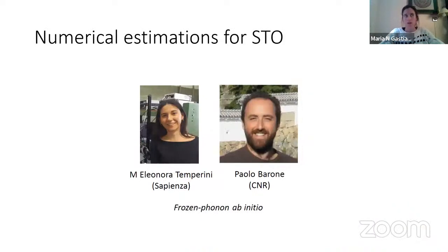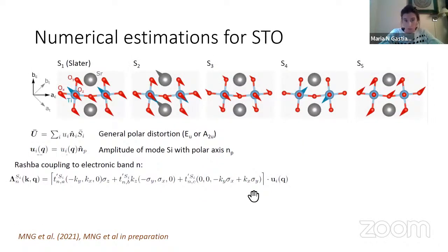And so I showed how you can couple to this mode. I showed what kind of superconductivity you can expect. And now let's do some estimation. So is this a pairing mechanism that is relevant for this system, for strontium titanate? In order to do that, what we did is work in tandem with this microscopic model and the ab initio frozen phonon calculations, and all those were done by Eleonora and Paolo, who are based in Rome. So the first thing that we had to do is freeze a phonon, and then you recalculate your electronic band structure in the presence of this phonon. And then from that reconstruction, you obtain the coupling.